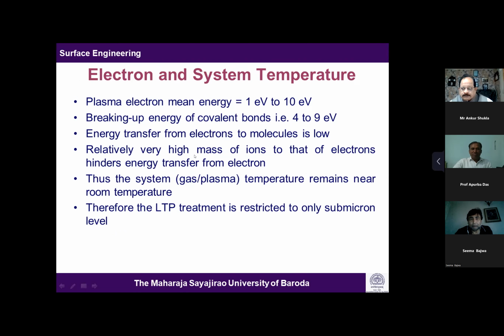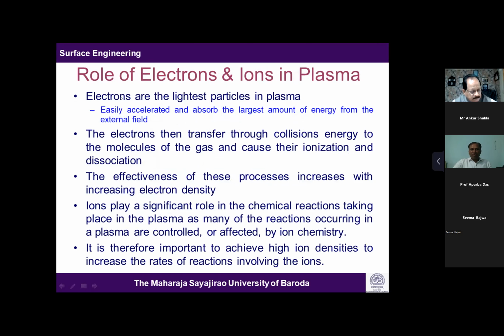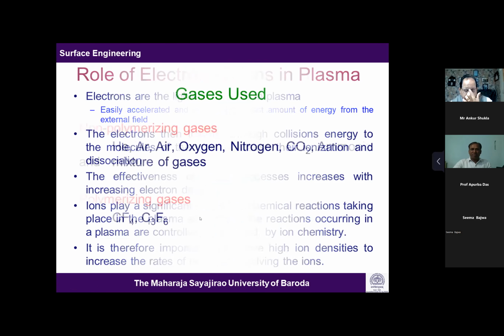The relatively very high mass of ions compared to electrons hinders the energy transfer from electrons. Thus, the system temperature remains near room temperature. This is the principle of low temperature plasma. And because of the same chemistry, the LTP is restricted to the submicron level of the substrates. Of course, the role of electrons and ions is important. The role of electrons is mainly to initiate surface radicals and chain scissions, and the ions decide the rate of reactions. I'm skipping this in detail because of time constraints.